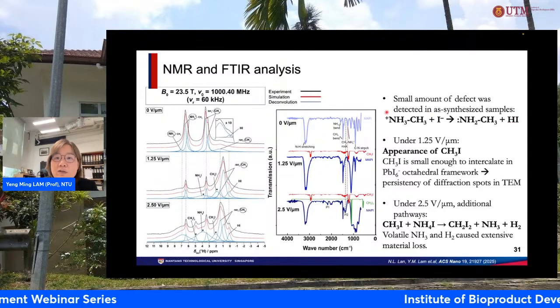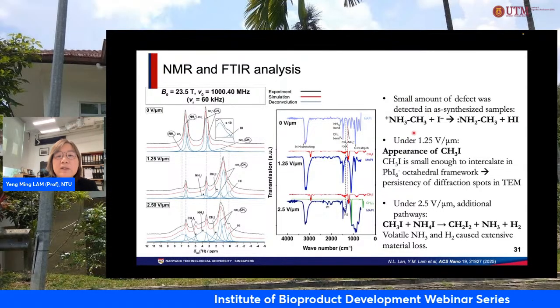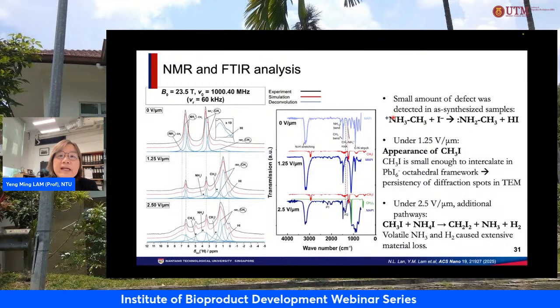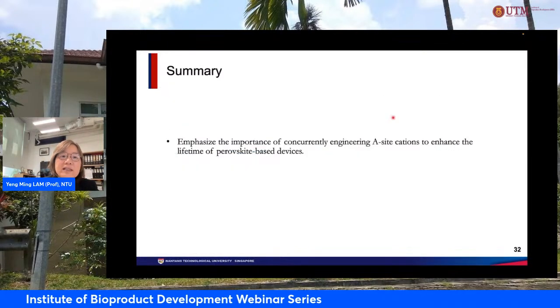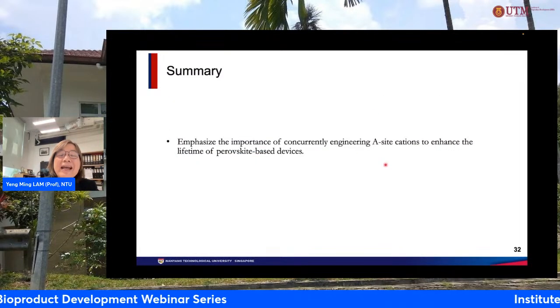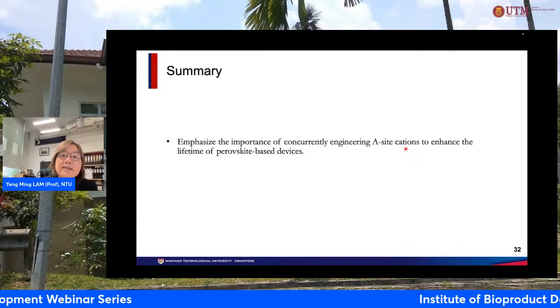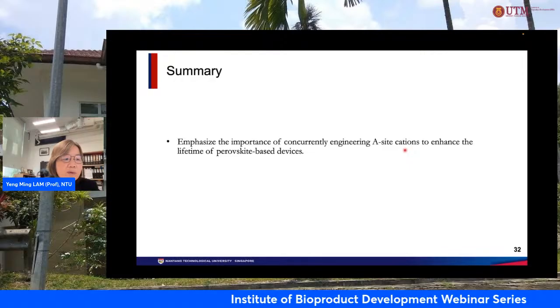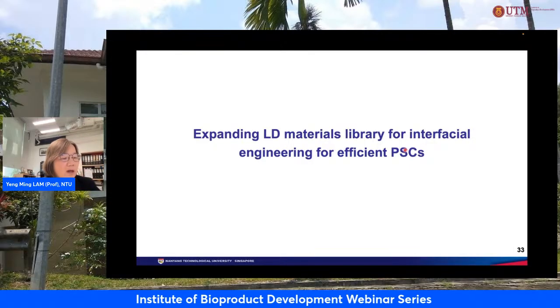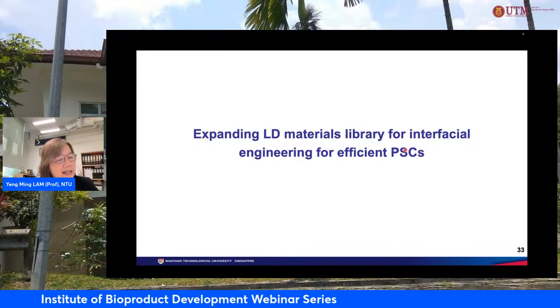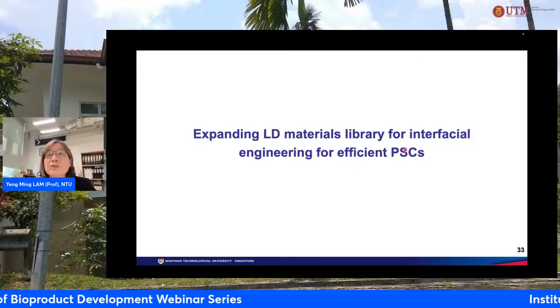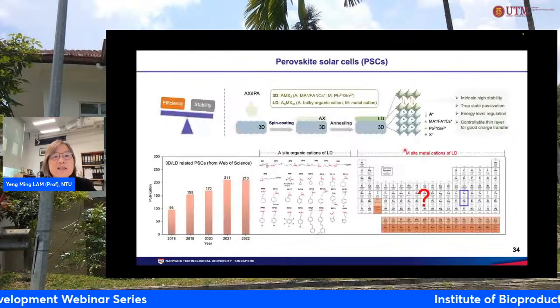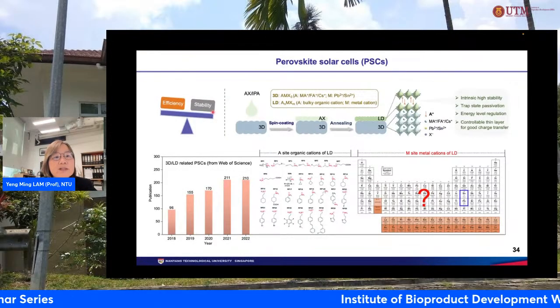So the cause of this is because of the cation that we are using. The way to then deal with this degradation is to engineer the A site cation, to change these A site cations. So what we did was create a platform where it's possible to expand this. We wanted to balance efficiency and stability.